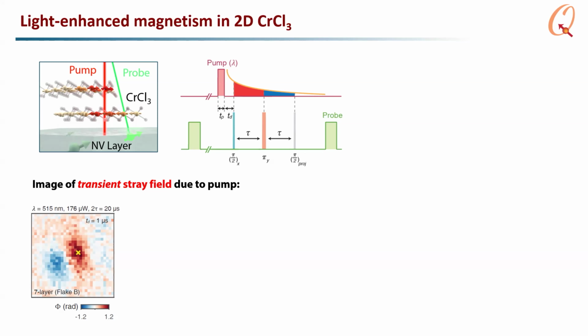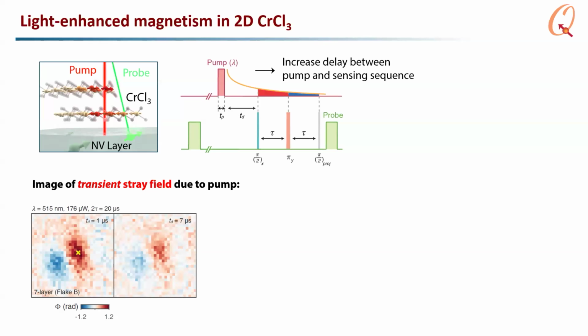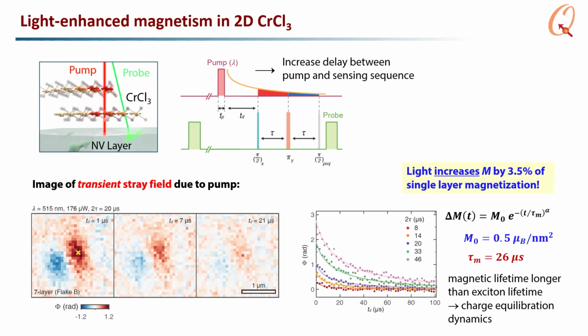and then do the same thing as our photocurrent. We can scan the green laser beam relative to the pump beam, so we can map the spatial profile of the transient stray magnetic field. We can increase this delay, and what you see is the transient stray magnetic field diminishes, and this transient pattern allows us to say that it's an increase in the magnetization, not a decrease.